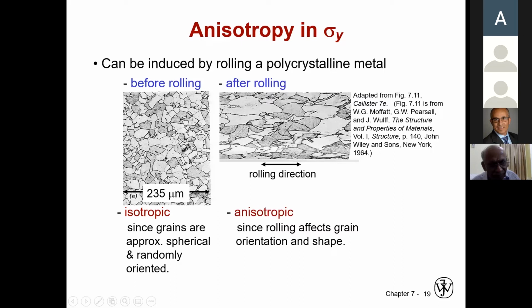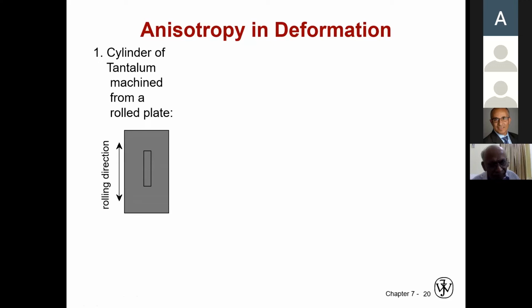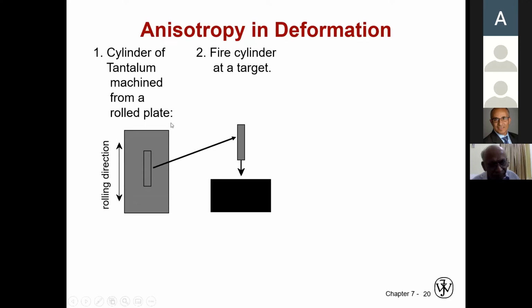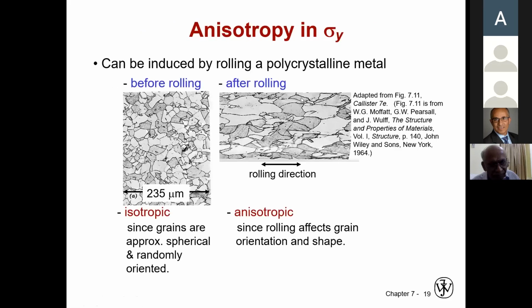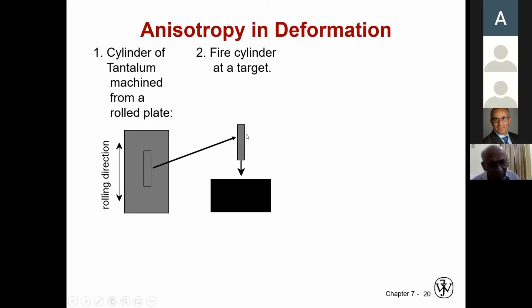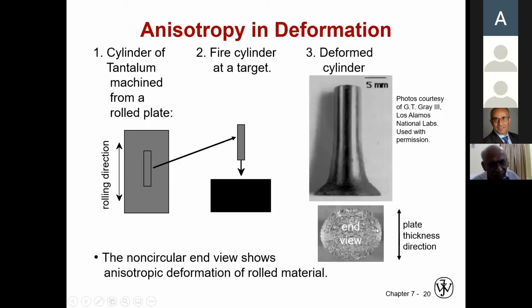Like the rolling that we use, for example, to make automobile bodies or any steel stamping plant. Now, if the material is anisotropic, for example, here is an anisotropic material, you fire a cylinder at a target. Now, this is a rolled plate, but the sample is a cylinder. However, it was rolled, so the bullet was made after rolling it. Now, if it is isotropic, the deformation of this bullet should be circular here. But instead, after you fire it, the bullet doesn't have a circular shape. It has an ellipsoidal shape because it doesn't have the same properties in, let's call it, the X and Y direction.